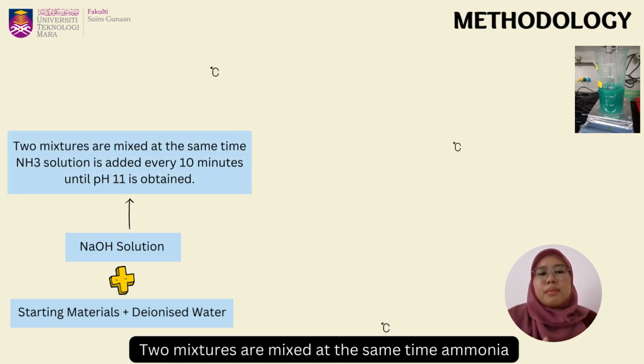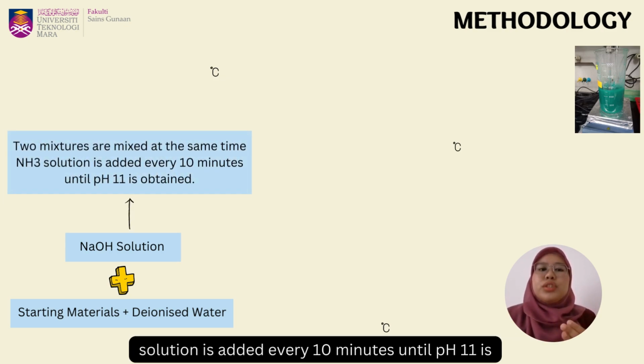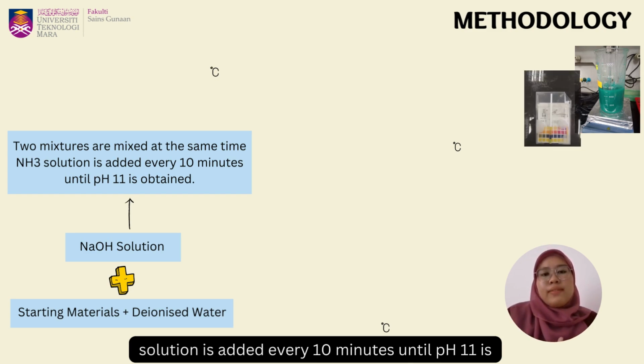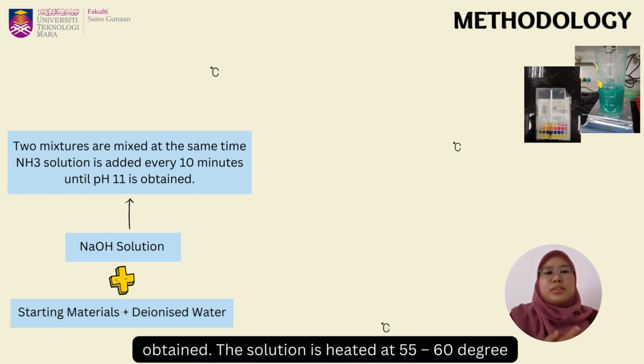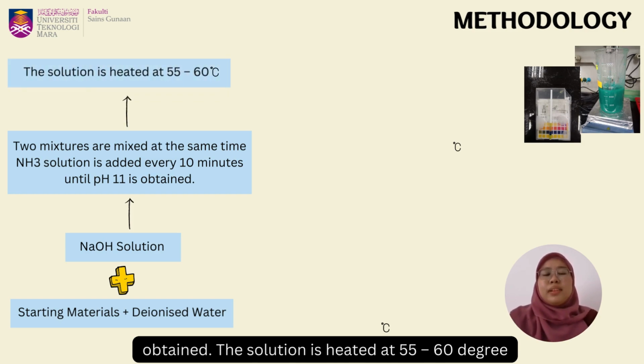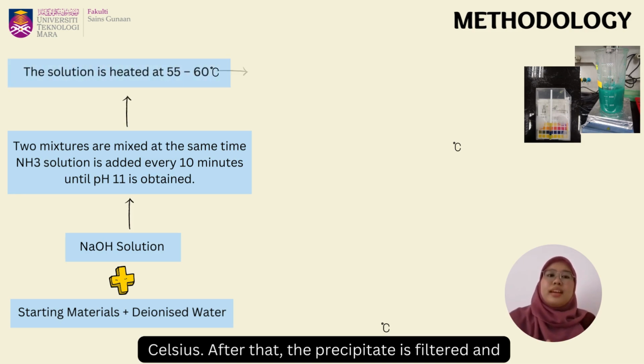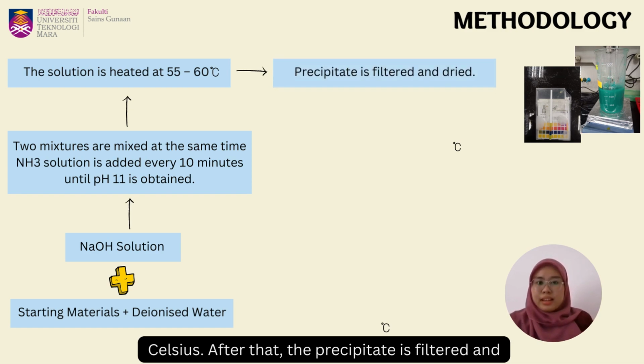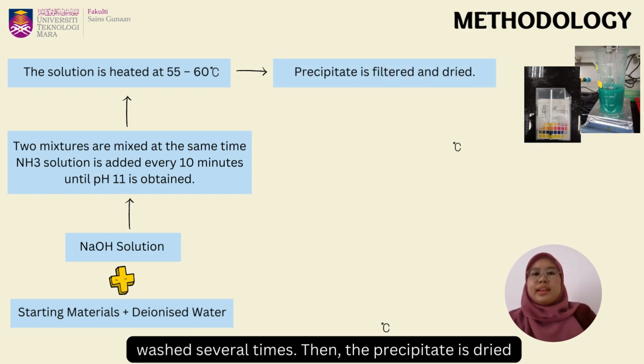The two mixtures are mixed at the same time. NH3 solution is added every 10 minutes until pH 11 is obtained. The solution is heated at 55 to 60 degrees Celsius. After that, the precipitate is filtered, then washed several times. Then the precipitate is dried overnight.